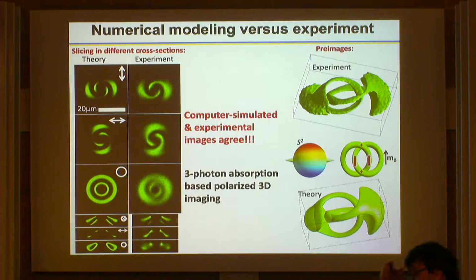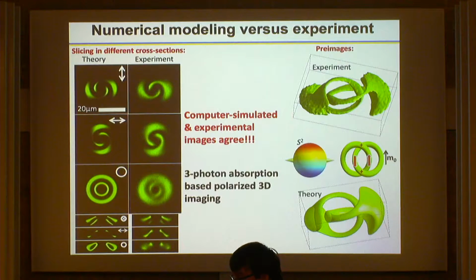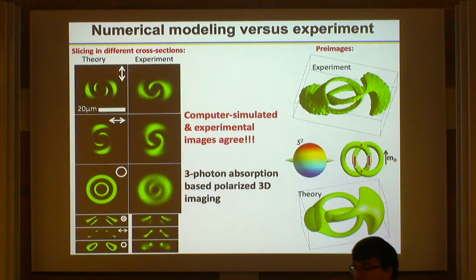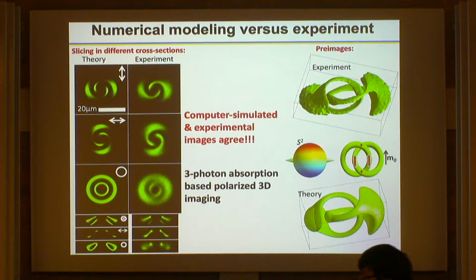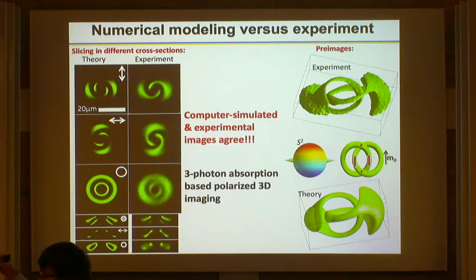So what's the material that was used in the experiment? It's a very common material, pentyl cyanobiphenyl, doped with chiral additive, CB15, and you add barium hexaferrite nanoplatelets. Okay, and it just forms these skyrmions all over the place? Well, yeah, so you form that material, you add chiral additive, then you have boundary conditions, and as you quench from isotropic phase, you have those conditions. Okay. Well, you have to set the boundary condition, no? Yeah, well, that's a very common thing. You need a uniform background for those things.